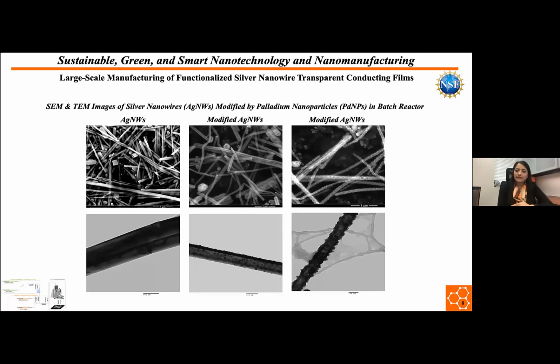Then the next step is how we can increase the stability of silver nanowires towards oxidation, because when silver nanowires are used in transparent conductive film manufacturing, they are prone to be oxidized in an oxidative environment. We have started to modify the surface of silver nanowires using palladium nanoparticles in order to increase their stability against oxidation. And here are some SEM and TEM results of silver nanowires, as well as modified silver nanowires using palladium nanoparticles at different galvanic replacement reactions,